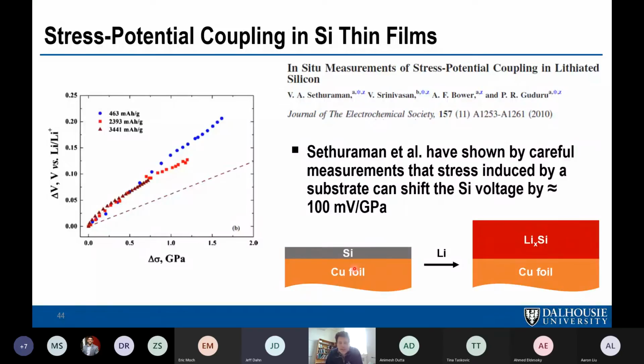So what you notice when you make these alloys is that the voltage curve of the silicon is not exactly the same anymore. It looks the same, but it can be shifted in voltage. That seems to be because of stress potential coupling. If you're restricting the silicon from expanding, it's going to be harder to put lithium in it. And that causes a polarization in the voltage curve. It shifts the voltage curve to lower potentials during lithiation because it's harder to expand. During contraction, during delithiation, things are more or less free to delithiate, so you don't see much of a shift during delithiation. You only see the shift during lithiation, where you get these compressive forces.